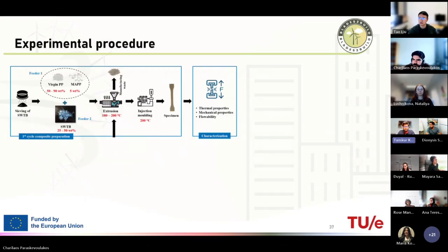In order to produce these specimens, we also have to follow certain procedures in order to get the material with higher properties. For that, as you can see on the screen, first we sieved the material which we received from one of our project partners, PreZero, and made sure we have the fibrous materials which can be used in the polymer composite as reinforcement material.